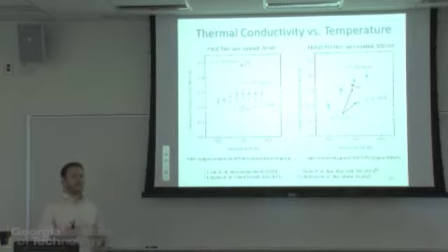In terms of the electronic contribution to thermal conductivity, there is a theoretical contribution that's typically in metals called the Wiedemann-Franz law. The electronic contribution to thermal conductivity is proportional to the electrical conductivity, and this is really true in free electron systems. So it may not be apparent in polymer systems, but there could be some contribution to the thermal conductivity.